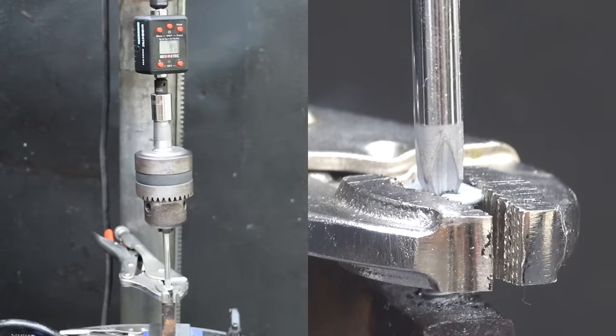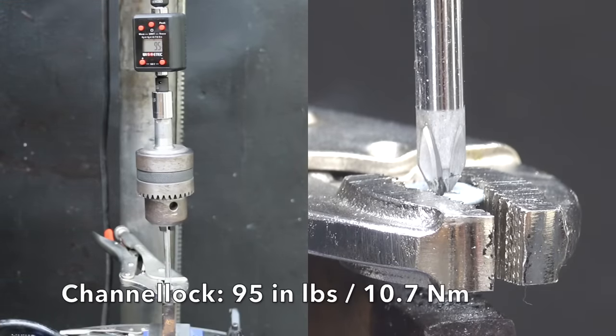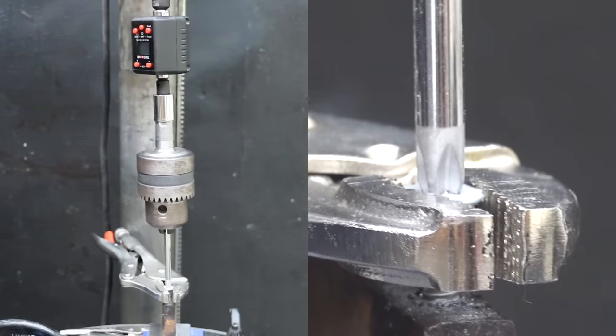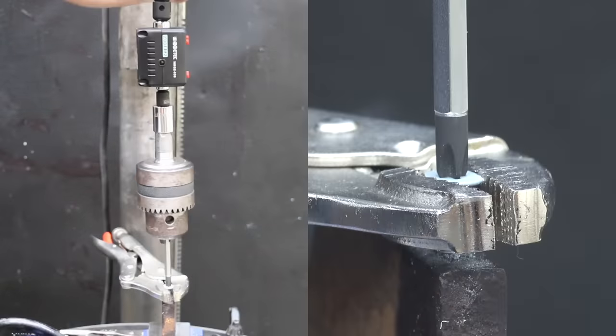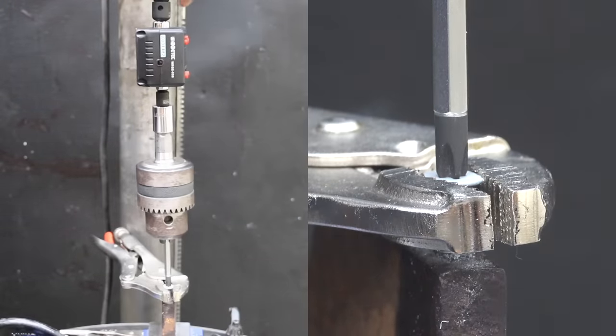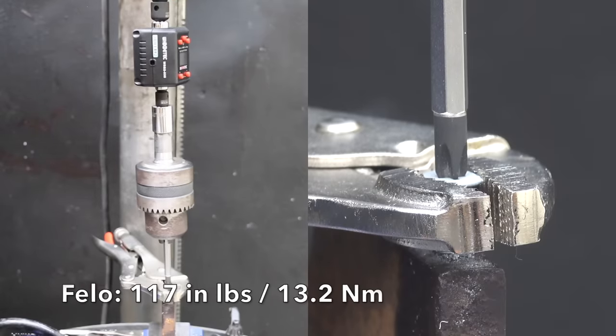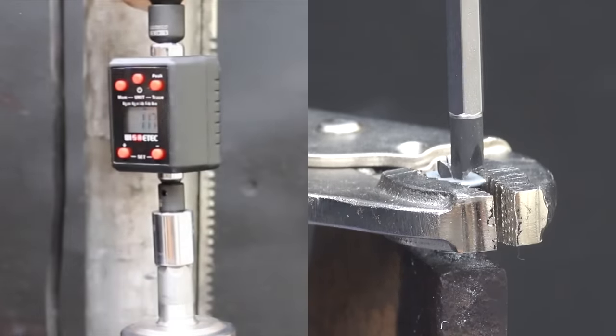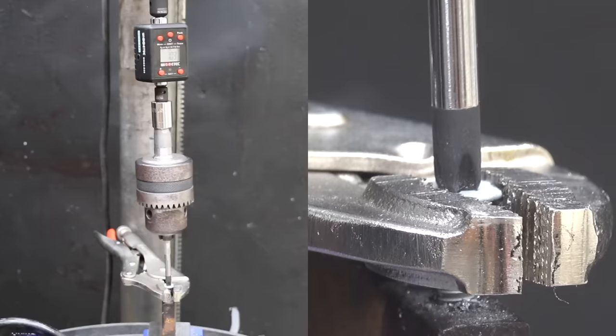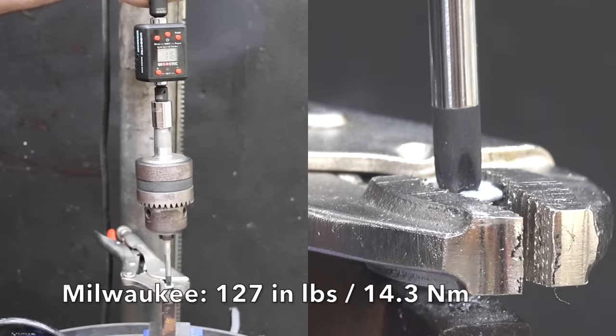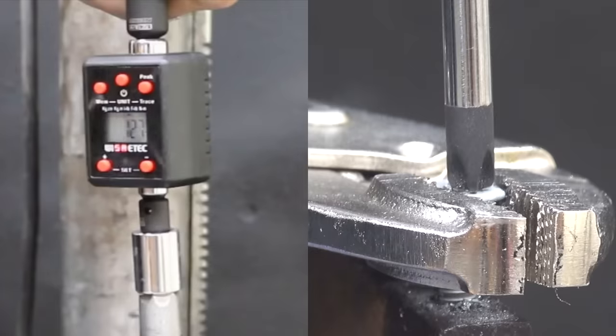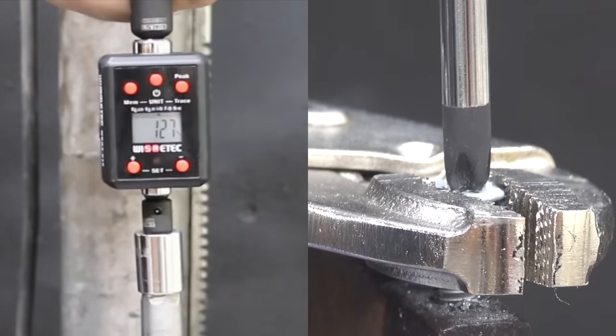And the channel locks performed slightly better than the Tekton in the first test, and they once again outperformed the Tekton this time, camming out at 95 inch pounds. And the Felo performed nearly as well as the Craftsman in the first test, but it came up 1 inch pound short of matching the Craftsman at 117 inch pounds before finally breaking. The Milwaukee performed just as well as the Craftsman in the first test, but the Milwaukee came out on top this time with a very impressive 127 inch pounds.